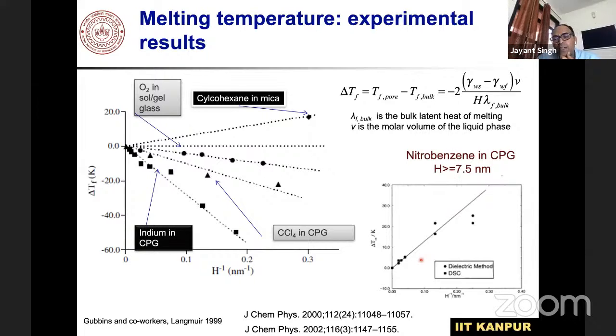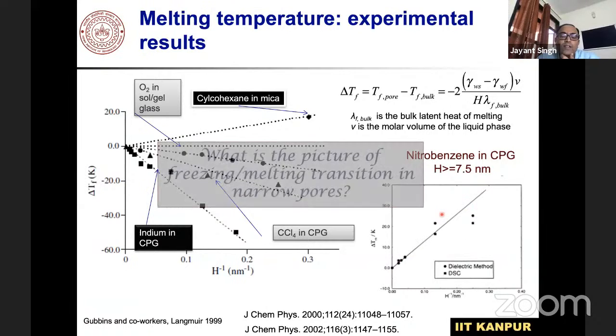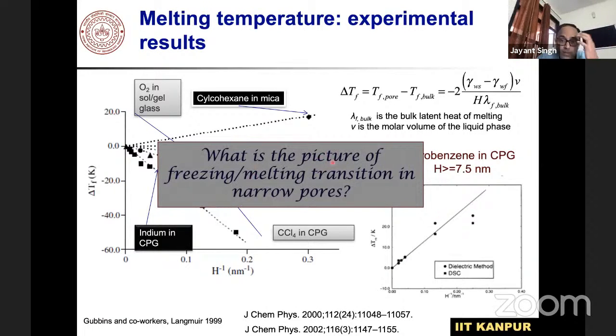Then we observed that maybe the linearity holds when the pore size is much higher, and it breaks down at a smaller scale. So this is where we started doing a little more in-depth analysis of what the picture of freezing and melting transition in nanopores is. When you define nanopores, you're saying a few nanometers, less than 10 nanometers. If you want to put it in terms of the molecular size of the fluid, then it's less than 8 to 10 molecular sizes of the fluid.